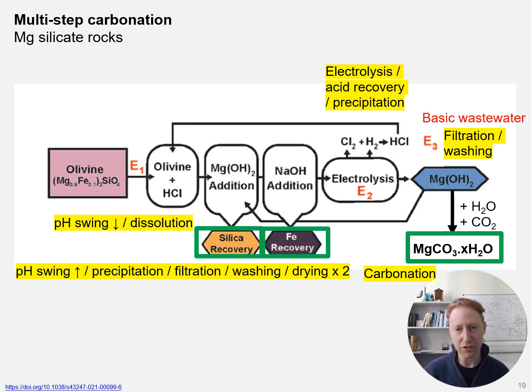example of CO₂ mineralization using olivine as the feedstock. The first step is to dissolve the olivine in an acid, which is here shown as hydrochloric acid. After this dissolution step, there is a controlled multi-step increase in pH to precipitate silica and then iron oxide. These products are separated, washed separately, and dried separately. After these solids are removed, hydrochloric acid can be recovered from the solution through electrolysis, and this increases the pH and also produces a magnesium hydroxide product. That magnesium hydroxide product can then be carbonated to form a magnesium carbonate product, and that then requires washing and drying as well.